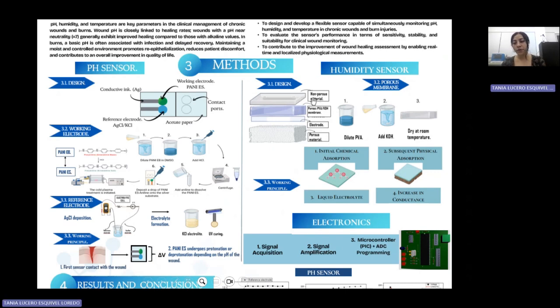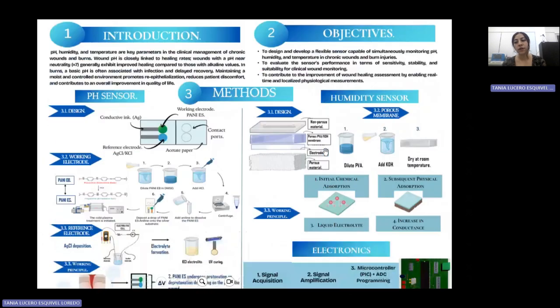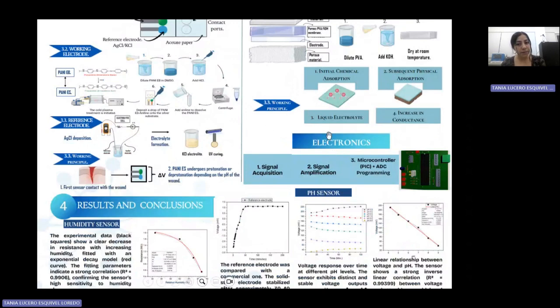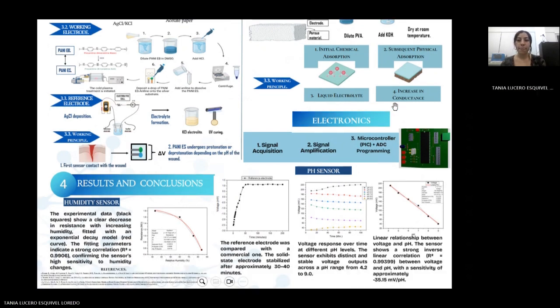They are covered by a non-porous material and by a porous material to let the sensor breathe. So the working principle is based on the fact that as humidity increases, water molecules are absorbed into the polymer. There's an initial chemical absorption by chemical bonds from water to the porous membrane. As the porous membrane is hydrophilic, there are bonds formed there. And then there is subsequent physical absorption by a reaction called the Grotthuss reaction. It's like a chain reaction in which some layers of water continuously form.